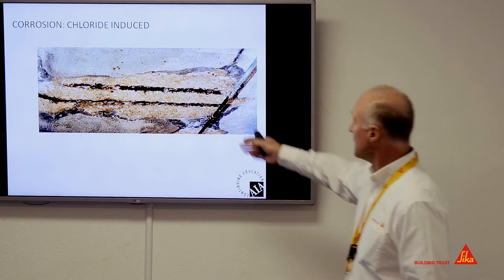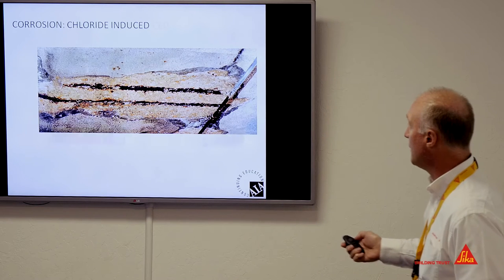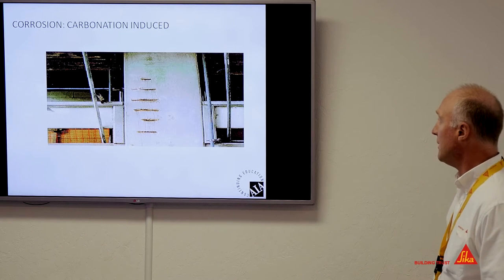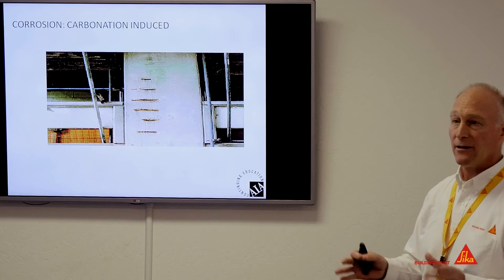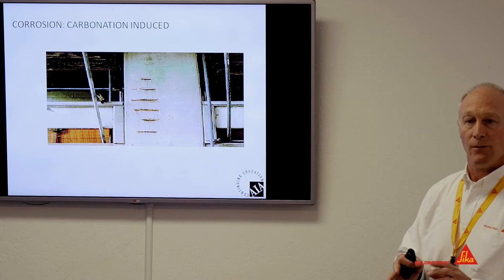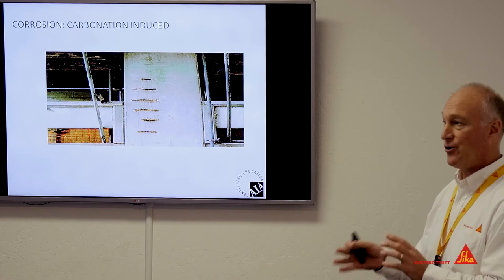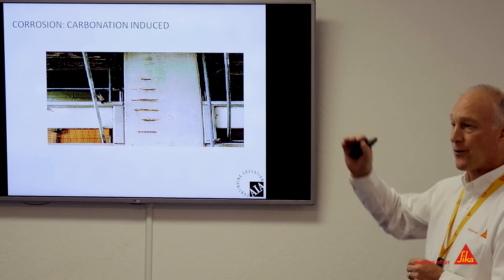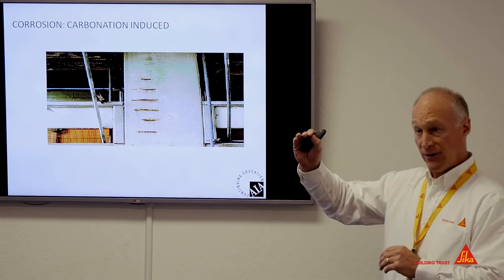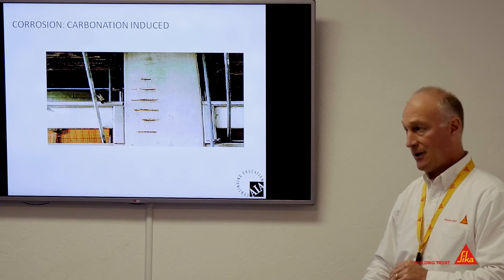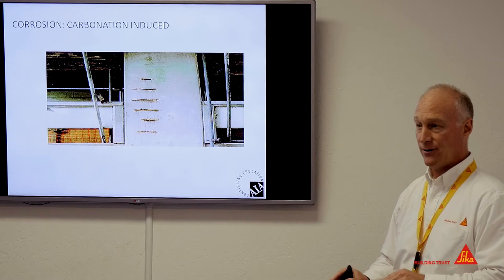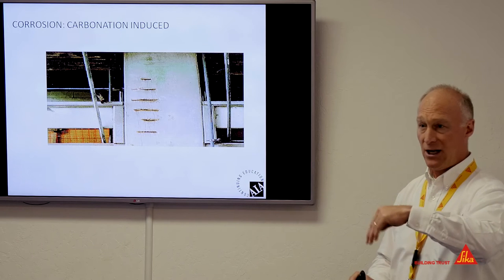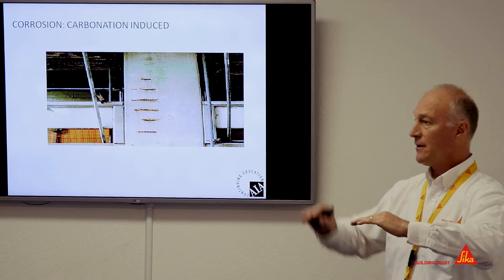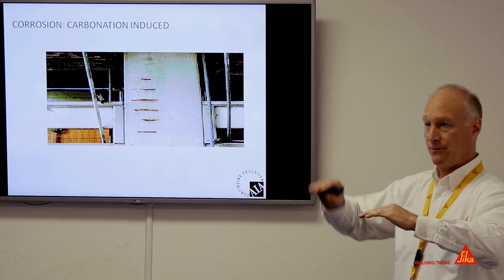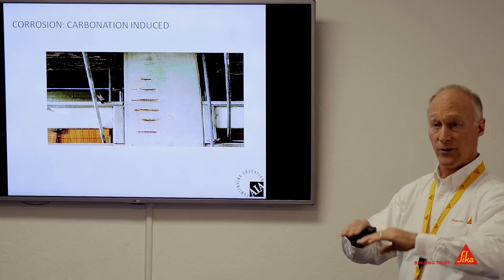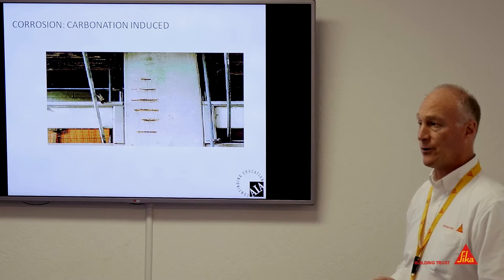So we see a lot of this: chloride-induced corrosion, we call it that, and also carbonation-induced. And it's not one or the other. A lot of times they both exist on the same job, and there is a synergy between the two. We talk about a threshold for chlorides. If it's in carbonated concrete, that threshold can actually go down to zero. You don't need any chlorides if it's carbonated. If the pH is somewhere in the middle, then the chloride level that would cause a condition for corrosion is maybe a little bit lower.